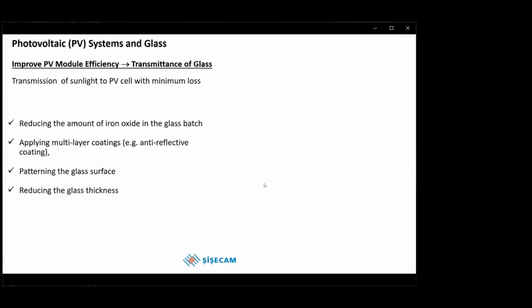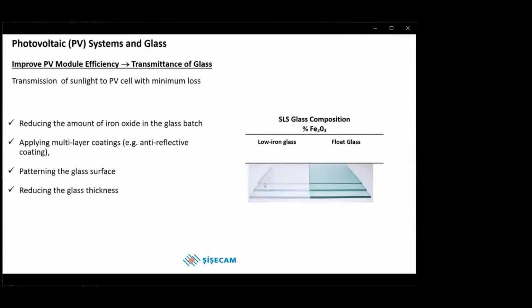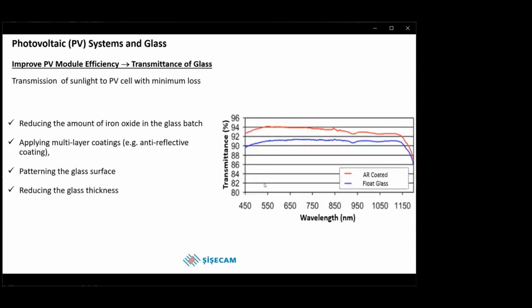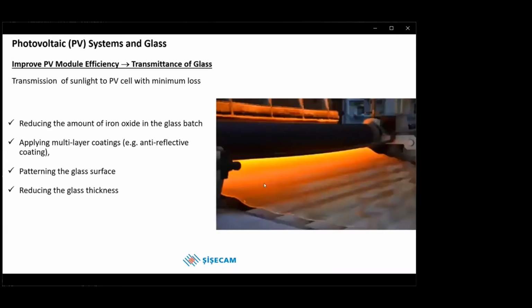The amount of energy produced in photovoltaic systems significantly depends on the properties of the cover glass. It's always desired that the sun rays passing through the cover glass reach the cell with the least possible loss. To get higher efficiency from photovoltaic systems, studies concentrate on different strategies, such as reducing the amount of iron oxide in the glass batch, applying multilayer coatings, for example anti-reflective coatings, and patterning the glass surface.